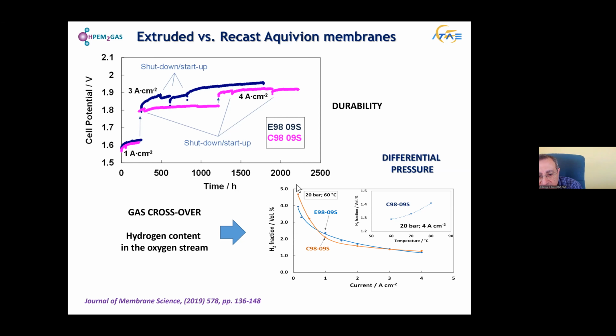But it can be critical at low current density, because at low current density we can achieve the flammability limit. The flammability limit is 4% hydrogen in oxygen. This must be avoided - the safe operating range is below 2% of hydrogen in oxygen. This is really an important aspect to address.